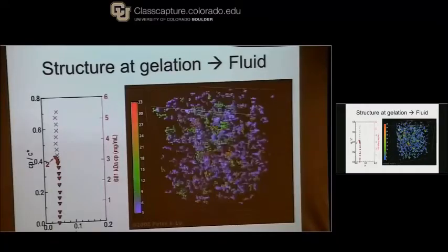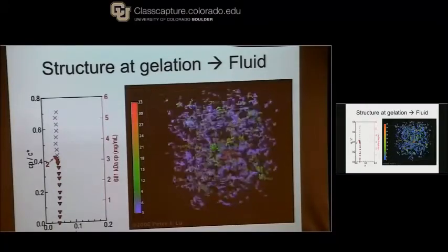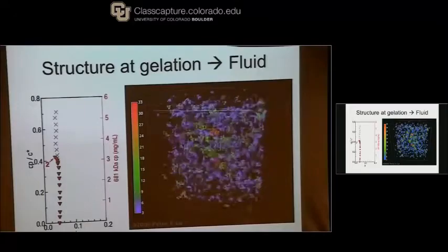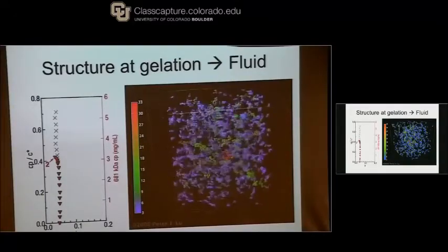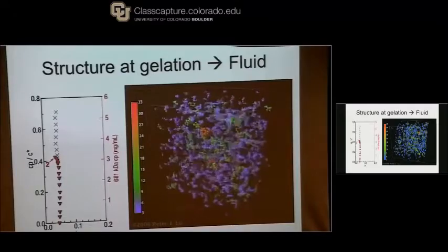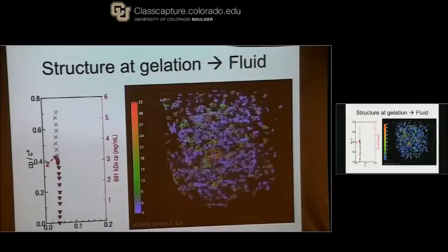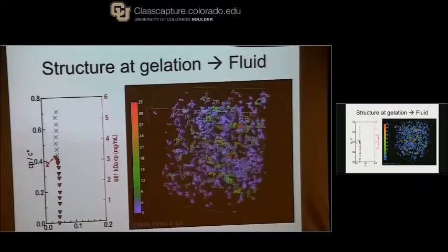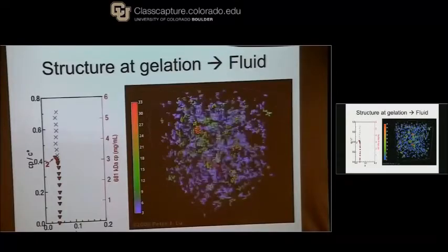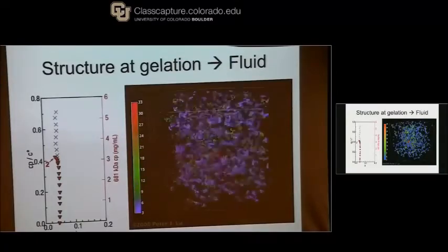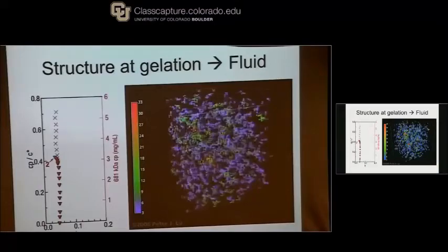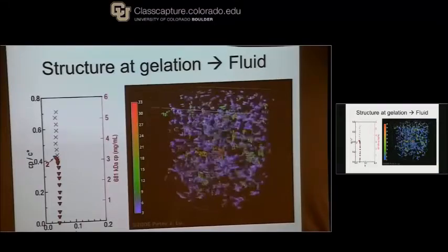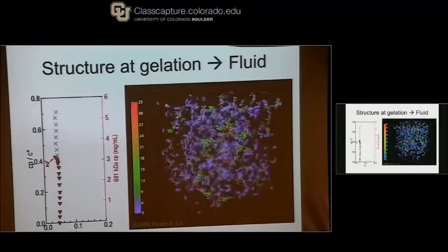Now, this sounds simple, and in principle it is: I can find two solvents that are good solvents for the particles, one a little more dense and one a little less dense, and I can just mix them till they exactly match. I can test that by putting them in the centrifuge and making sure that no matter how hard I centrifuge, the particles never sediment.